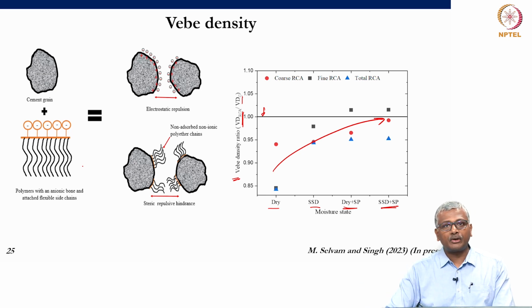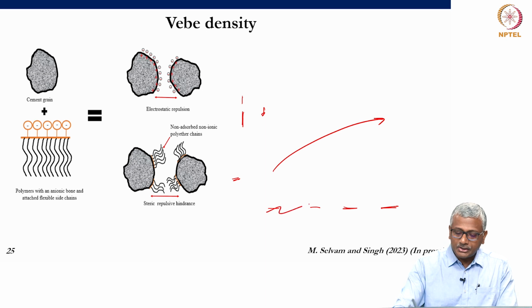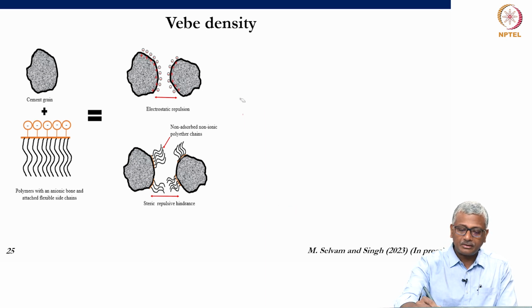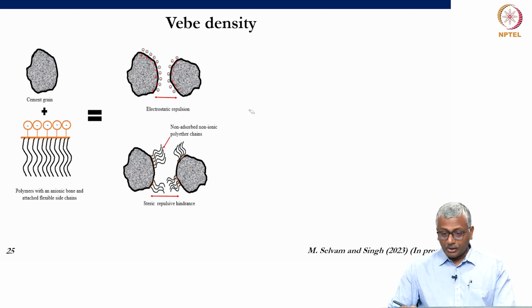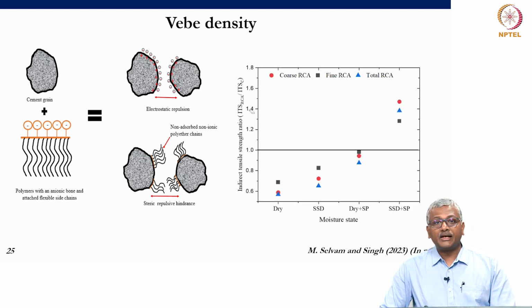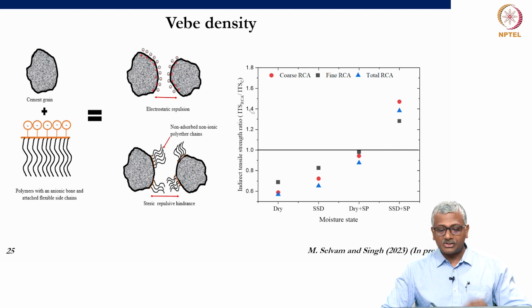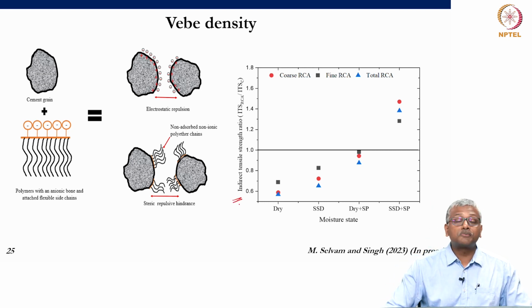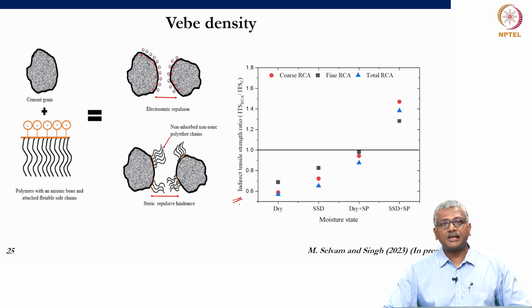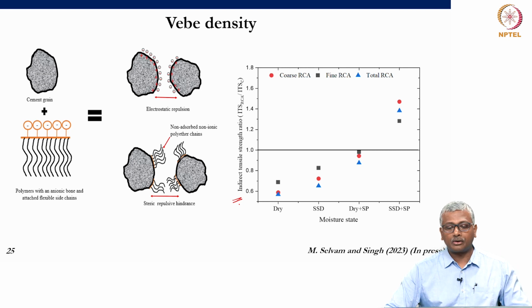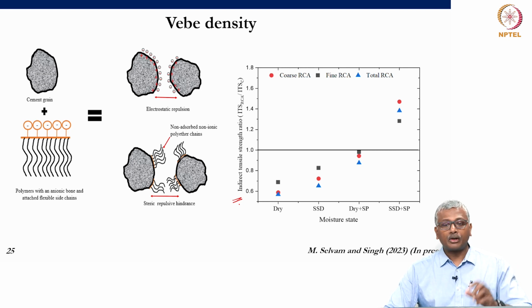Okay. So, what happens here is, this aspect of use of superplasticizer not only affects the density and gets it to a level which is equal to conventional aggregate, it also tends to help you, let me just rub this off so you can see the next graph. It also tends to help you in actually achieving a good property from a concrete in terms of the tensile strength. So, here indirect tensile strength or split tensile strength by the Brazilian technique was determined for concrete with normal aggregate and concrete with recycled concrete aggregate, roller compacted concrete.